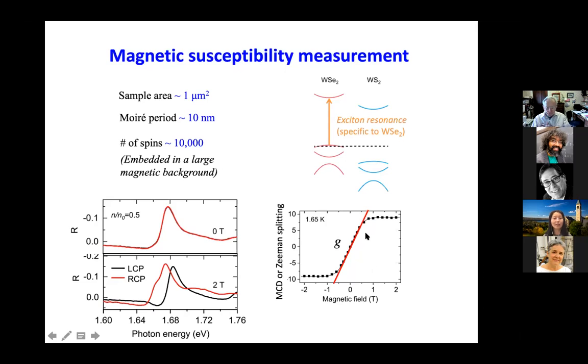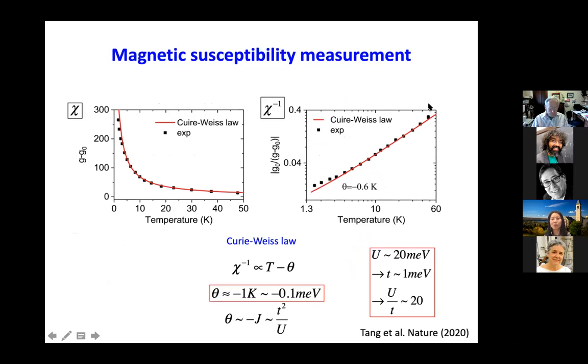So this actually fits the localized moment picture nicely, right? If you apply a smaller magnetic field, you try to align those localized moments, but then above a certain field, all the moments will be aligned by the magnetic field. So to get the magnetic susceptibility, we just need to look at that slope, right? Because this is equivalent to the M-H curve, magnetization as a function of magnetic field. So the slope is the susceptibility. So we can get the slope and take 1 over the slope as a function of temperature. And you can see that indeed, at high temperature, it goes linearly. And if you extrapolate this curve, it hits the x-axis at a negative value. And this tells us that the interaction is antiferromagnetic.